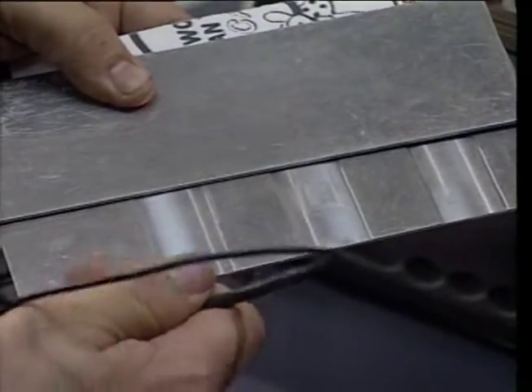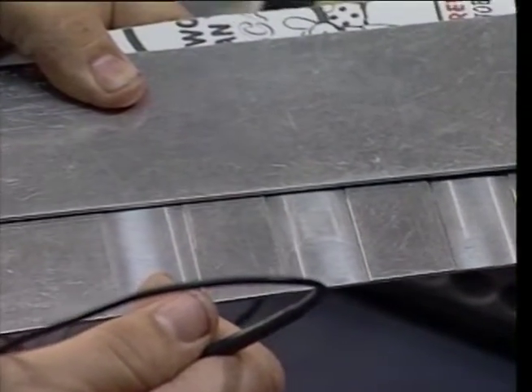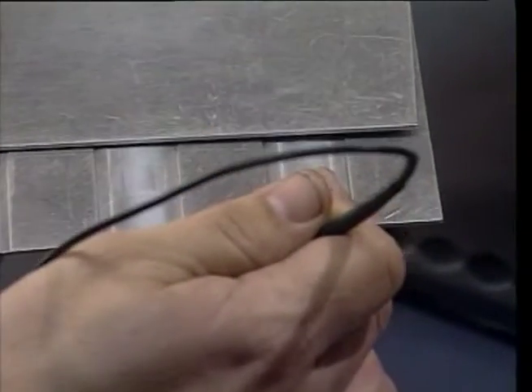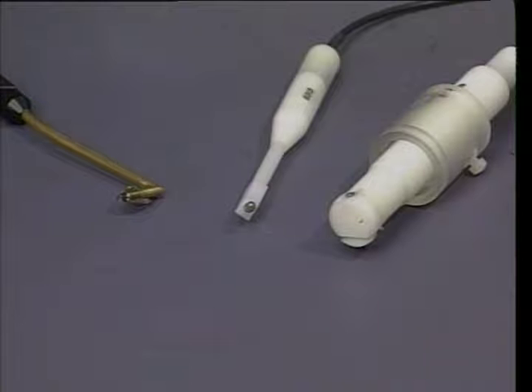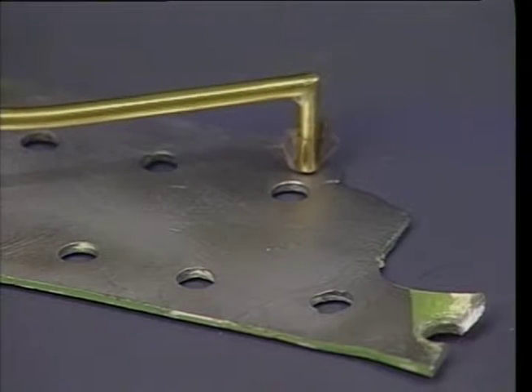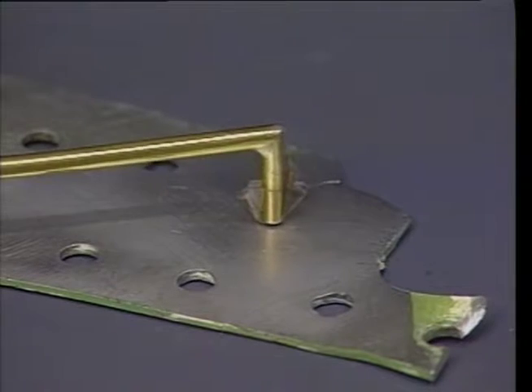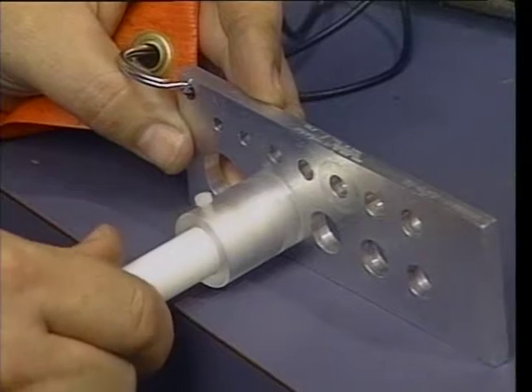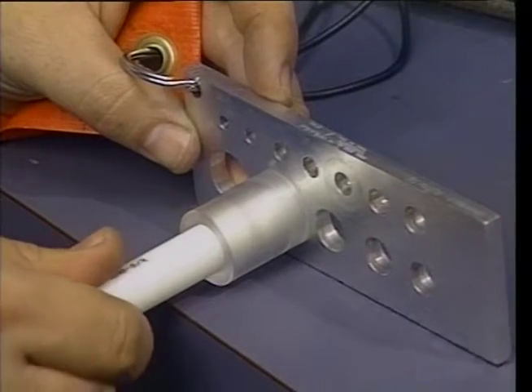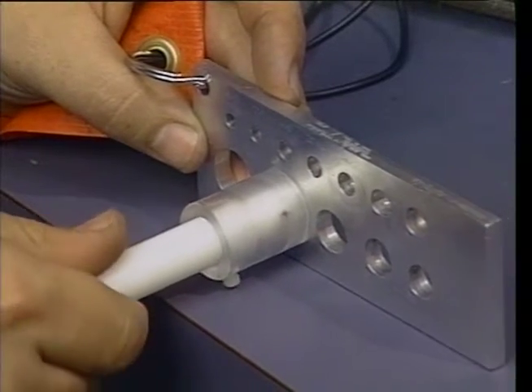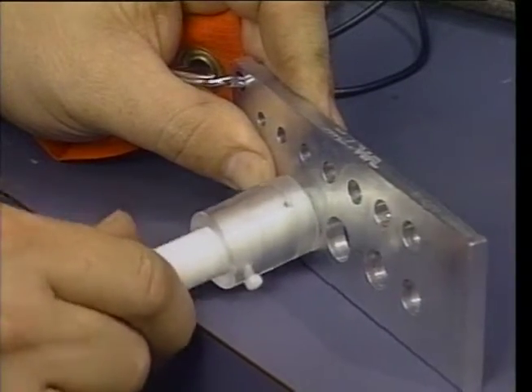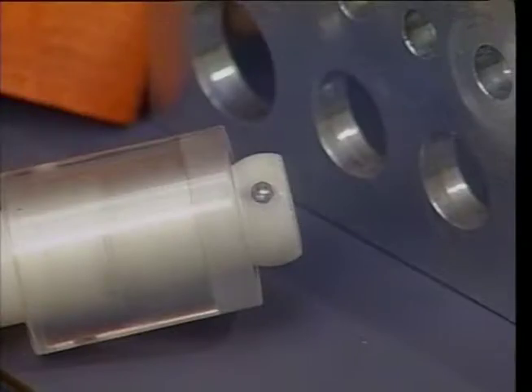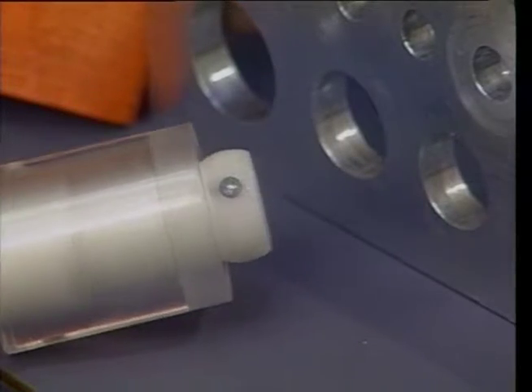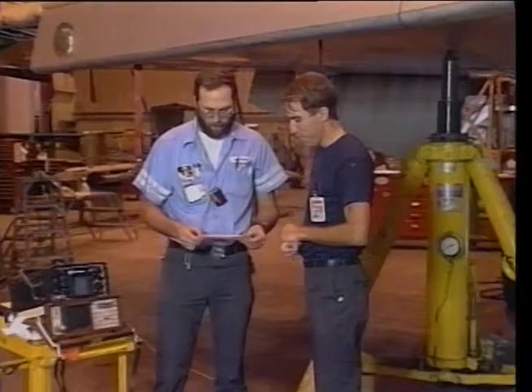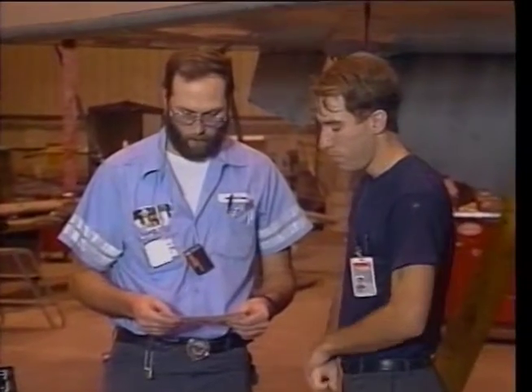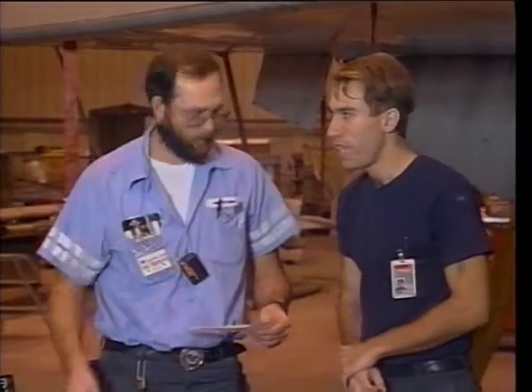Low-frequency eddy current testing can be used to detect cracks and thinning caused by corrosion in multi-layered structures. High-frequency eddy current tests employ small diameter probes, like this right-angle probe, and can detect small surface cracks and flaws. Special tests use custom probes. For example, here's a bolt hole probe, which is rotated 360 degrees while inserted in the hole and can detect surface corrosion and cracks. Eddy current is one of the most frequently used tests to measure depth of corrosion or corrosion loss.